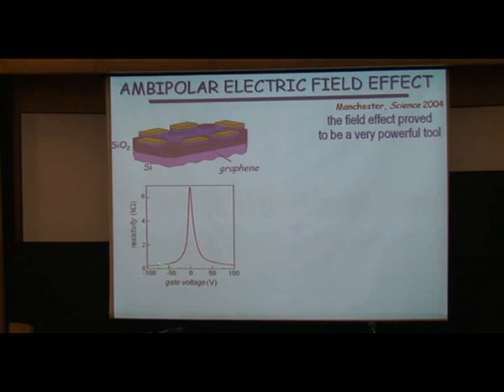What we found in the very first work is that when you apply a so-called gate voltage, a potential, to the substrate through a silicon oxide layer, you pump in electrons or you repel electrons out, and you see the so-called ambipolar electric field effect, where resistivity rapidly goes down when you increase the number of electrons and goes up. The speed of this tells you a lot about the quality of this material, and the field effect proved to be an absolutely amazing tool to study physics in graphene. So we use this gate voltage as a routine tool to see what phenomena we get.